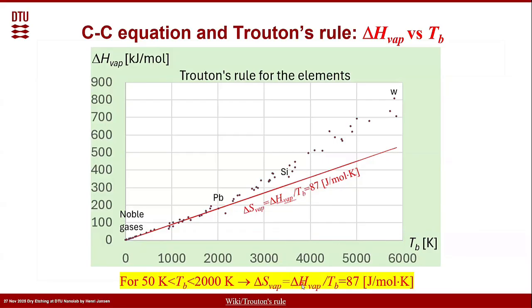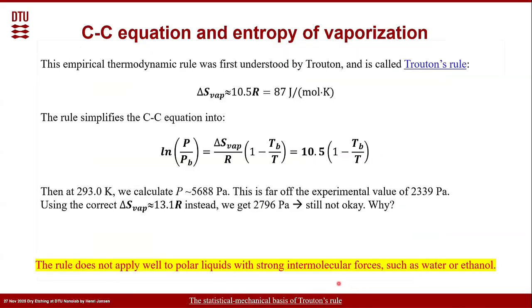So that's good news. Whereas the enthalpy of evaporation was changing with the boiling temperature, the entropy of vaporization is not. And we can see that even though it is not completely correct here, and if I would zoom in at the very low temperatures, it's a little bit below it. If you have a substance with a boiling temperature between 50 Kelvin and 2000 Kelvin, you are pretty sure it can be very close to the 87. It's not always true. For water for instance, it is a little bit off, but that is because of the property of water, it is a polar molecule. But most of the substances are at 87.